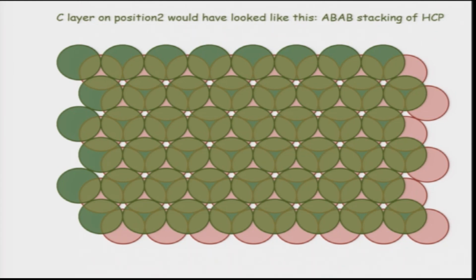So this is called AB type of packing, because now you have only two different positions, A and B, and the third again goes on top of A. There are actually crystal systems where you see this, and it is HCP systems. In HCP you get AB type of packing in the 0001 direction. So this is the HCP type of system.